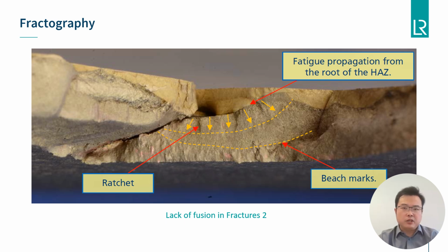For this case, the beach marks and the ratchet marks from the second part of the fracture demonstrated that for the bottom half of the fracture, the fatigue fracture has initiated from the heat-affected zone in the middle of the material into the propeller casting. The discontinuity at the edge between the heat-affected zone and the casting can only be explained by the lack of fusion during welding.